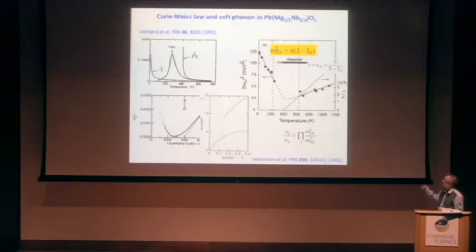And so there must be another excitation below this phonon, and our chairman, Sergei Vakhrushev, found some hints of this second phonon softening below this phonon's frequency, but it was very difficult to see it in neutron scattering because it is practically overdamped.